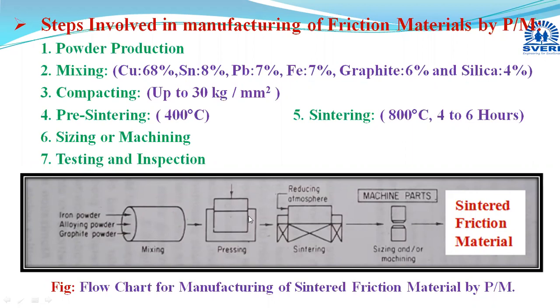The first stage is filling the die cavity with the help of a feed shoe or hopper. Then the volume is adjusted by raising or lowering the lower punch, and after filling the die cavity, it is leveled with a sweep. We are just sweeping it. This leveling is done, and now pressure is applied with the help of punches. You can use one punch to apply the pressure, or both punches can be used simultaneously to do the pressing operation. Now here the compacting pressure used in the manufacturing of friction material is less than 30 kg per mm square. After sufficient pressing,